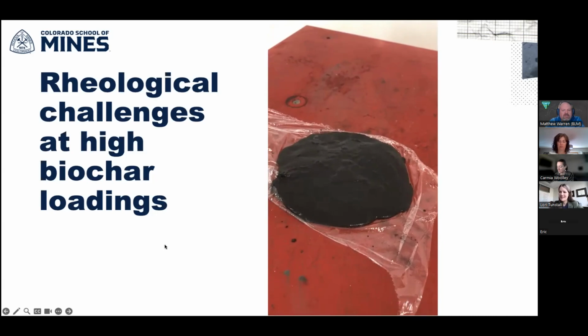Yeah, Matthew, do you have a comment on that? Yeah, so when we talk about oil well cementing, you're going to be trying to pump this through a 1 or a 2 inch piece of pipe at depths of up to 15, 20,000 feet. And the video that you show there, you absolutely would not be able to use that consistency for that type of plugging. And because of those depths, there's no way to vibrate that casing. Especially because a lot of times that casing does have cement from the primary cementing operation on the backside, which would reduce the effect of that vibration anyway. So you're going to have to keep this to where you can pump it through some fairly small sizes at some fairly long distances.